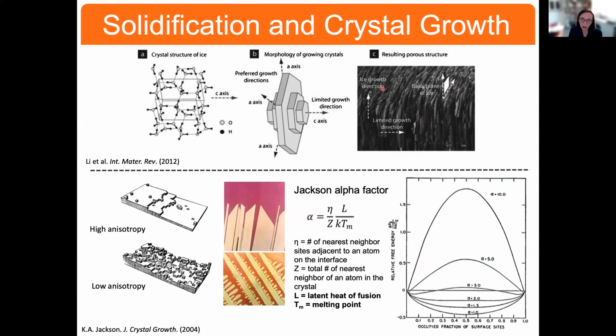Now, there's another aspect here that plays an important role. And the parameter that we have used to help us define this is known as the Jackson alpha factor. Basically, it's this Jackson alpha factor that will tell us that on solidification, whether an atom will attach to a surface in a very preferred place, as shown here in this diagram on the left, where we're developing a highly anisotropic structure, or if on solidification, that atom, as it attaches to the solid surface, doesn't really care. And you would end up with this below, where you have a structure with low anisotropy.